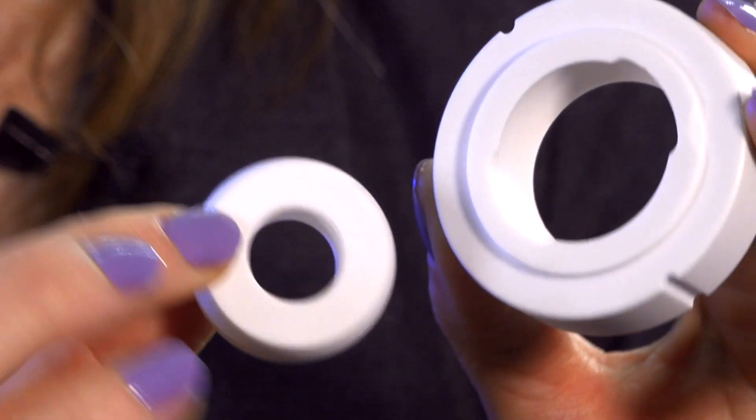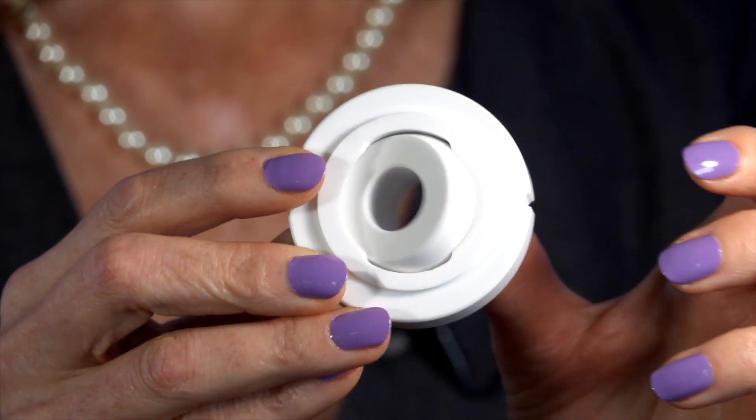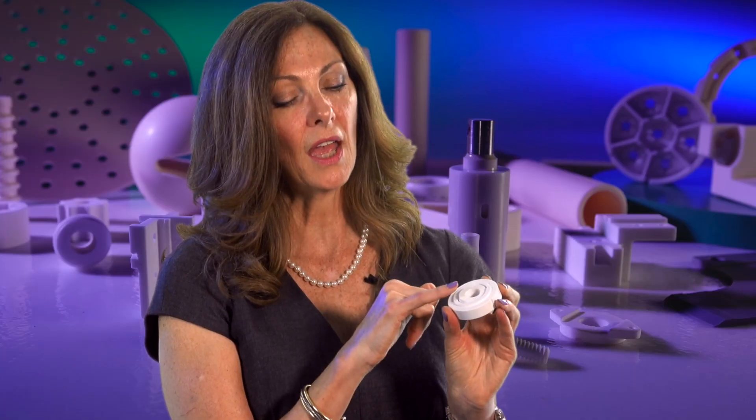The tolerance between the inner bearing and the outer bearing is about one thousandth. The surface finish of the ID of the outer bearing and the OD of the inner bearing match perfectly. They're at a 6 RA, so they spin perfectly and they wear evenly.